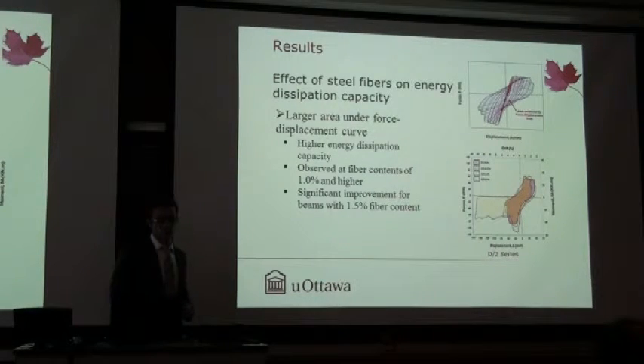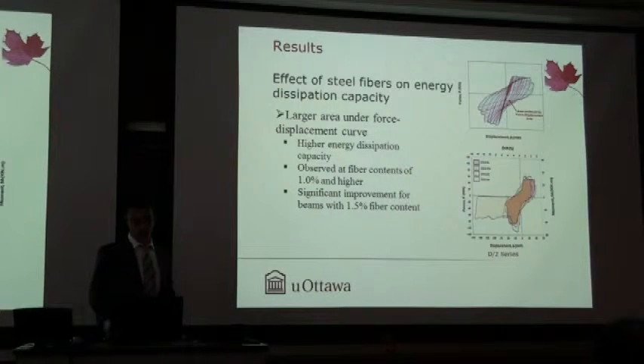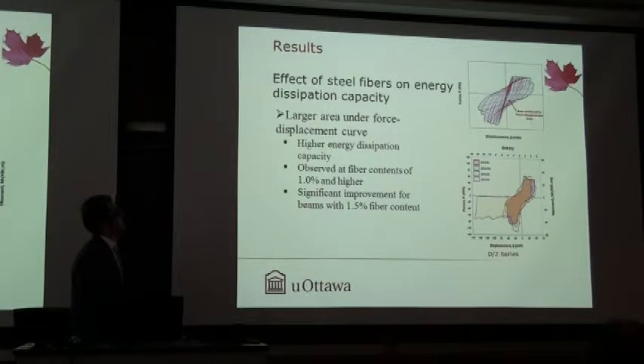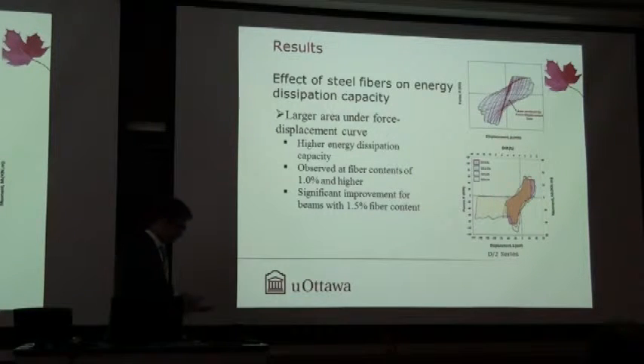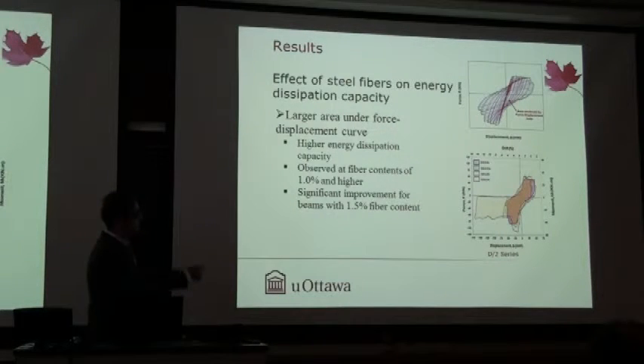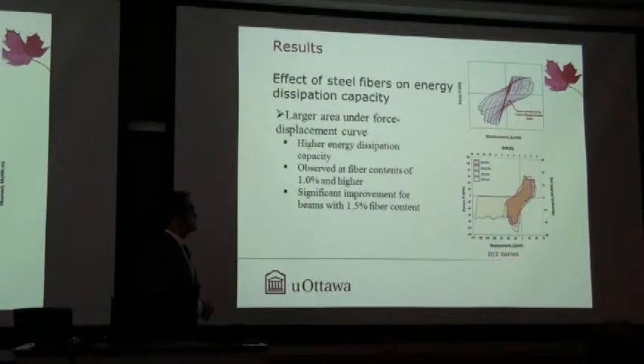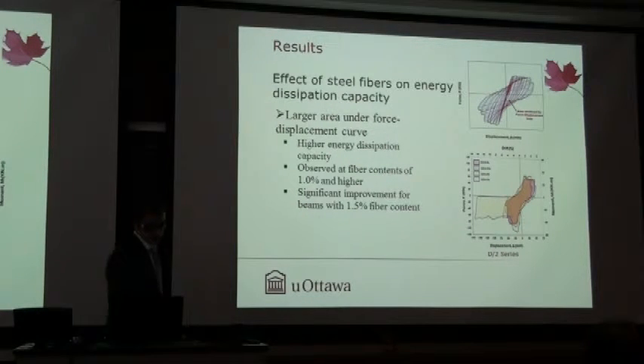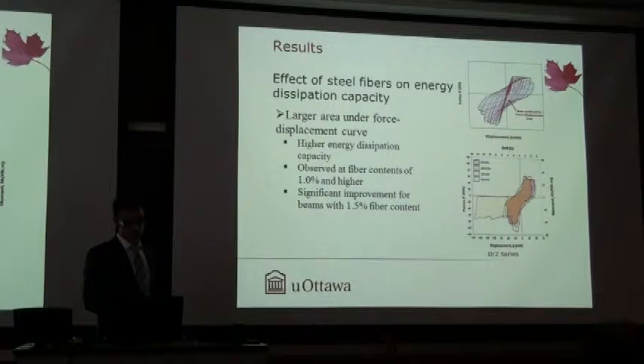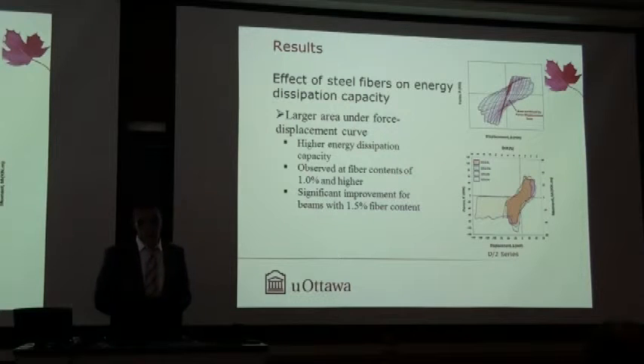In the first step, we did the load force displacement first, and by doing that, we tried to compare the improvements resulting from the application of steel fibers. As you can see, those are the force displacement diagrams, basically areas enclosed by force displacement diagrams for my D/2 series, and we observed that the energy dissipation capacity for beams with higher steel fiber contents increases.